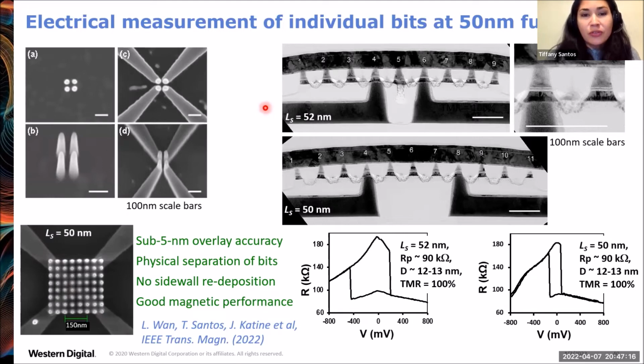The top one is for a 52 nanometer full pitch array, and the lower one is for a 50 nanometer full pitch array. And you can see excellent E-beam alignment for individual MTJ pillars on top of the bottom point contacts. You can see physical separation of the bits with no sidewall redeposition, and good magnetic properties, because we do get the testing of individual bits showing TMR of 100%.